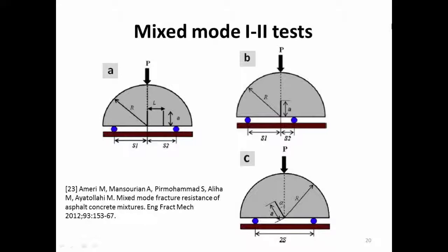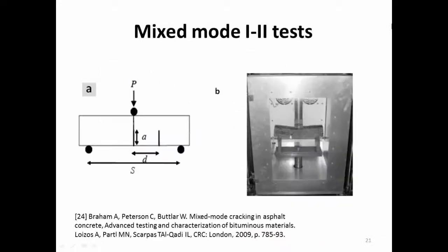The third one is someone said, okay, I don't want to shift the crack, just tilt it, and you will also get the mixed mode 1-2 result. And by using the finite element method, we can study different mode scenarios for this test. Similar things also happen if you shift the notch in an SEMB test from the middle to the side. You can also get this mixed mode crack.